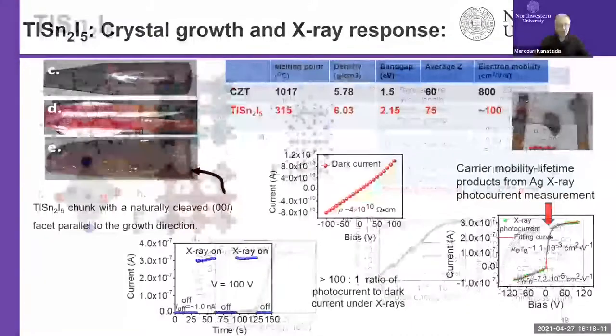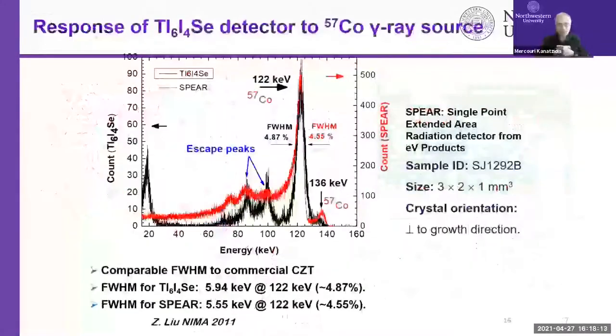Unfortunately, we could not reproduce this spectrum subsequently. And we worked for another 2 or 3 years on this, since 2011, and we were not able to reproduce it, not knowing why, even though we made some very, very pure materials. And therefore, then we gave up, unfortunately. Now I have an idea of why this didn't work. We couldn't reproduce it, and it may become obvious later in the talk.